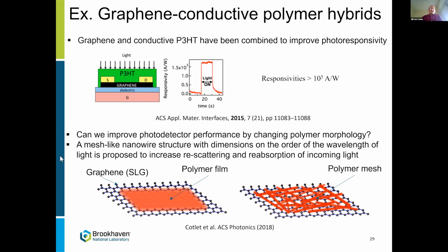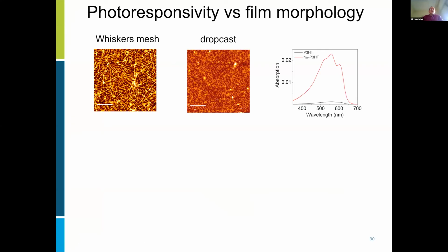So we go from a thin film on top of the graphene to something like a mesh, a nanowire mesh. So we deal now with nanowires out of the polymers, basically. In doing that, we can apply a method called the whiskers method, where the polymer dissolved in a good solvent is thrown into a bad solvent, and it forms a mesh structure formed out of nanowires, compared to a drop cast polymer of the same material. Controlling the concentration of the polymer and the molecular weight, you can get the voids in this nanowire mesh to dimensions similar to the wavelength of light.